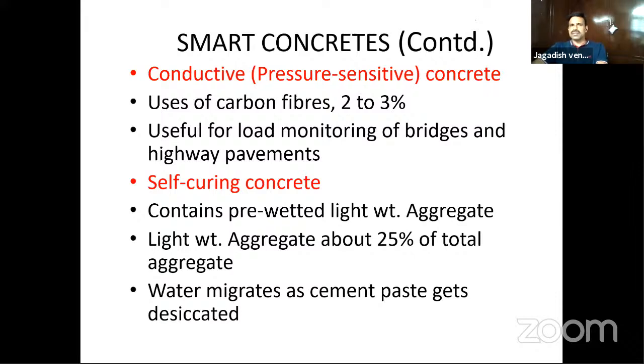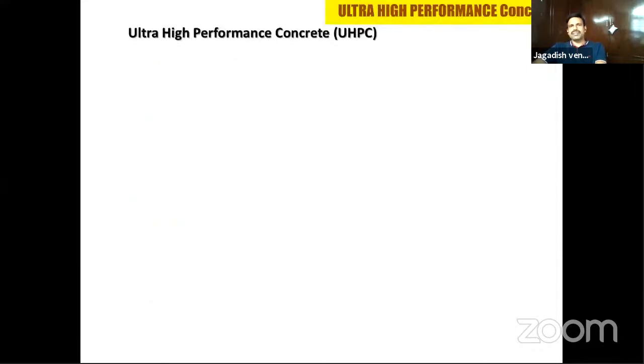There is a pressure sensitive concrete, when you use carbon fibers, 2 to 3%. So you can actually monitor the load of bridges and highway pavements. And there is a self-curing concrete, wherein you can use a lightweight aggregate that holds the water inside and slowly this water migrates to the cement paste. The hydration keeps happening.